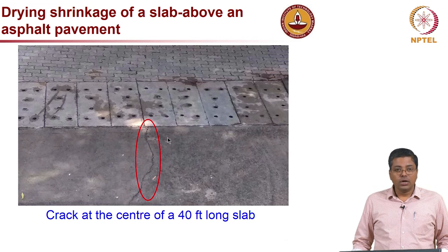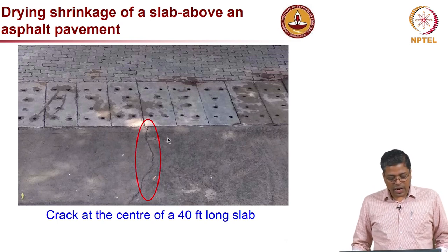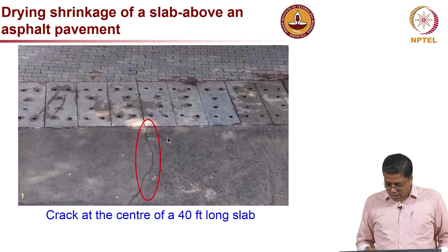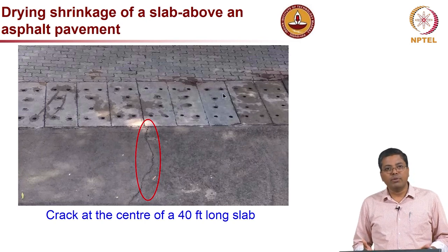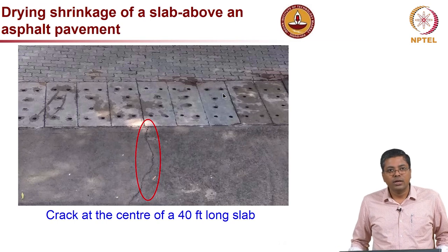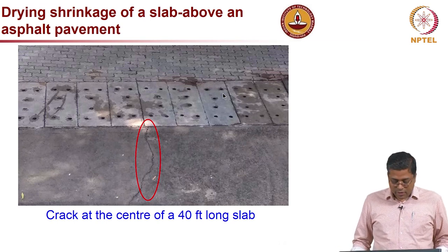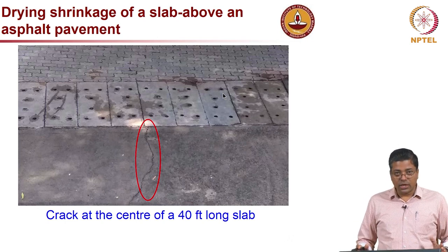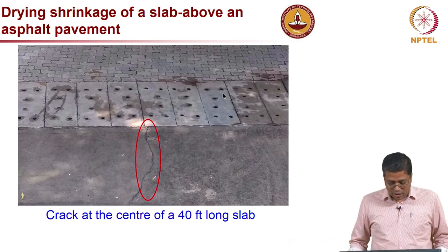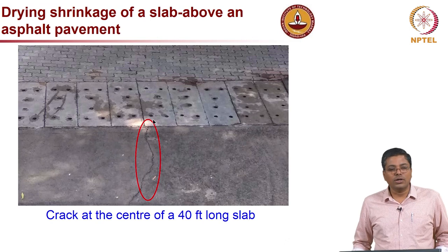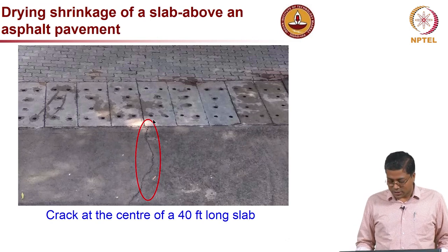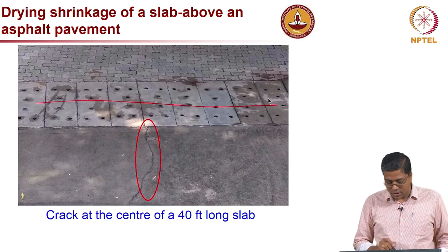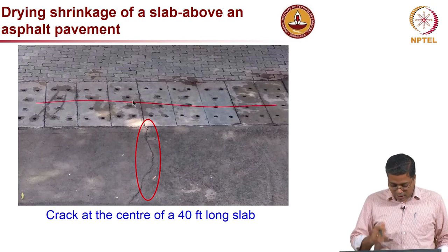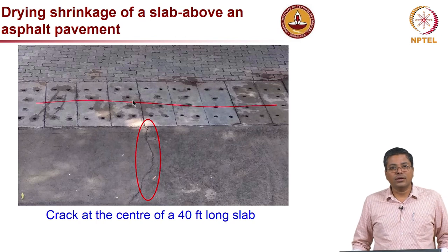This is an example showing drying shrinkage of a slab above an asphalt pavement. Because of the asphalt pavement below the slab, the restraint provided by the pavement is relatively less, which leads to this type of shrinkage. And this is a slab which is about 40 feet long, and only one crack is visible on this slab. And what you see here is a culvert, and on one side of the culvert the slab is provided, and only one crack.